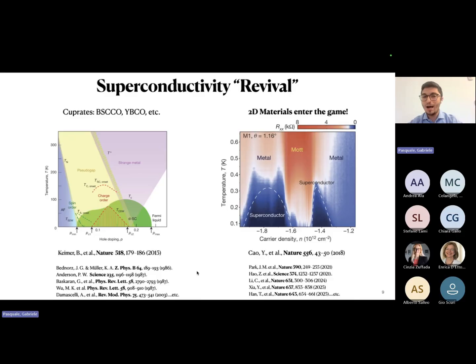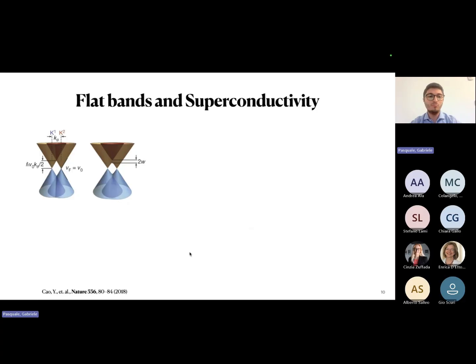So now we have only carbon atoms in this system. So how does superconductivity really emerge in a material which is way simpler than the cuprates? It turns out that the currently most accepted theory is that superconductivity in this material emerges because flat bands emerge. Upon twisting, the band structure of graphene kind of merges, and as you hit the magic angle, this flat band dispersion forms and superconductivity can emerge.